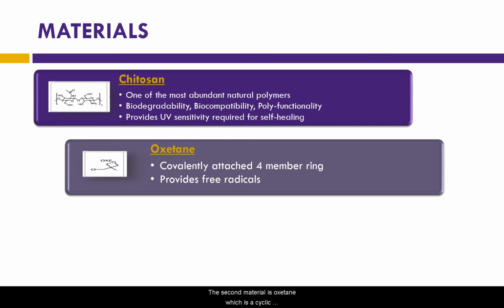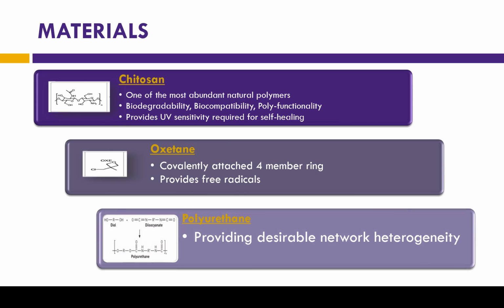The second material is oxetane, which is a cyclic ether compound and was opted to deliver a four-member ring. Cleavage of the four-member oxetane ring results in the production of free radicals. The third material is polyurethane, which is produced through an isocyanate polyol cross-linking reaction. The importance of polyurethane is to provide mechanical integrity and to facilitate the cleavage of the oxetane ring. These three components were selected based on their functionality.